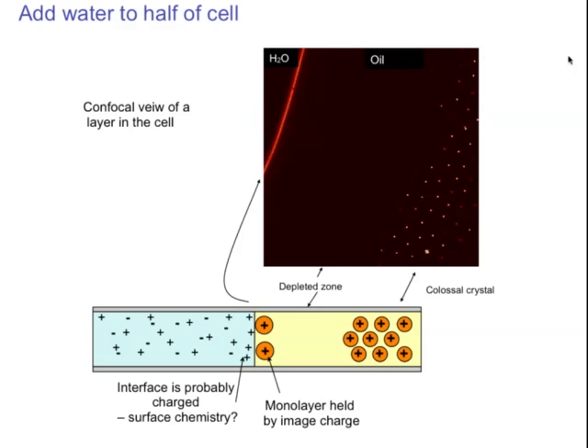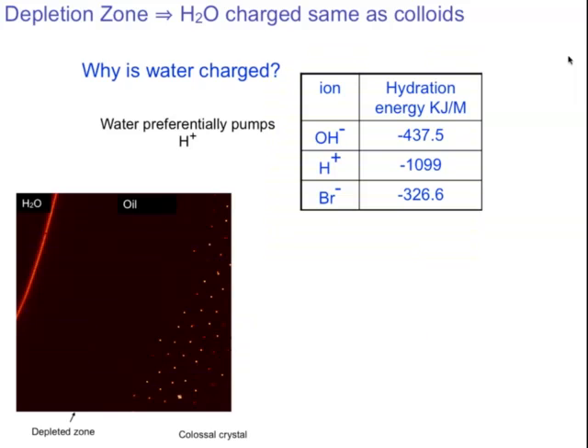This was completely unexpected. We didn't understand this. The fact that you have a repulsion here between the water droplet and the colloid suggests that the water droplet is charged. And it's charged with the same charge as these colloids, and that's what's repelling them. If that's true, and it turns out it is, it's because I'm just a physicist, and I don't understand chemistry. To me, the interaction of an ion with water is minus epsilon e squared over 2. But any chemist will tell you, no, that's part of the story. There are also hydration energies and the configuration of the water around the ion. And if you look at the literature, you find, although all ions like to be in water, the hydration energy of protons is much higher than negative ions, like OH minus or bromine. So although the water sucks all the ions out, it preferentially sucks protons out, and that leaves it positively charged.